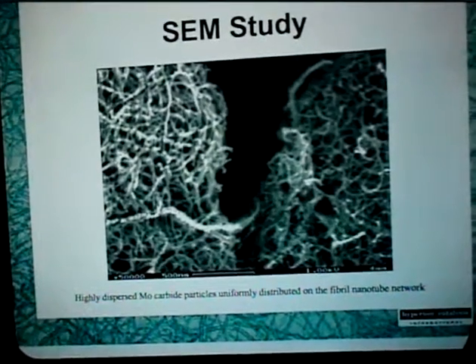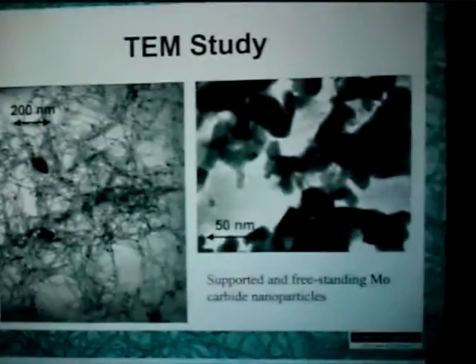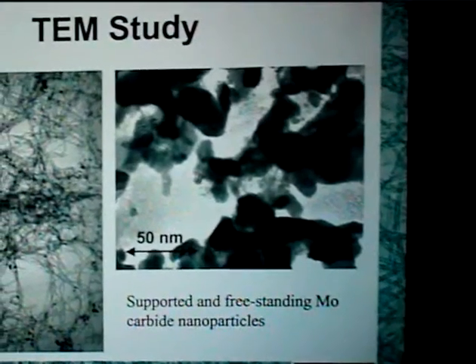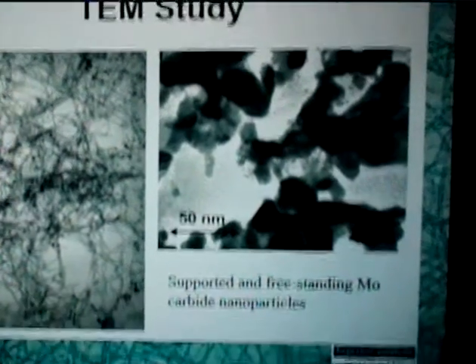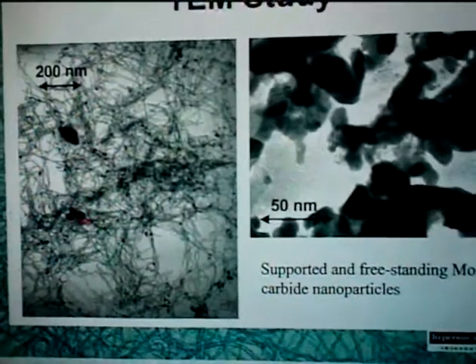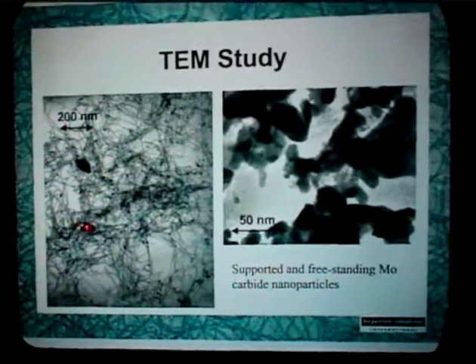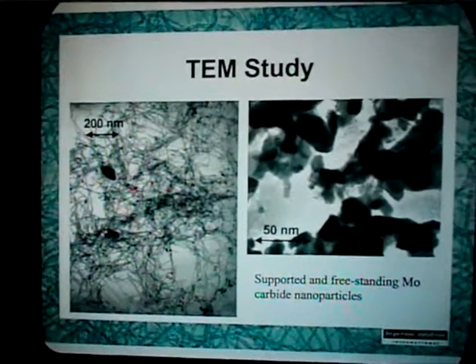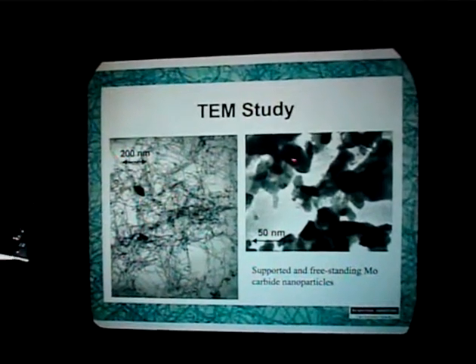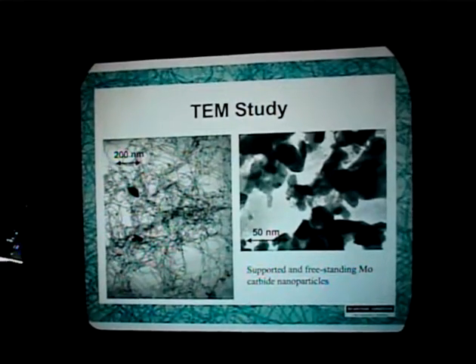So the important part is that we keep the structure of the fibril. And here is a much better picture, a TEM picture. Of course, those size of the particles depends on what is the loading that we have on the carbon. This is a low loading. Those are pretty large molybdenum carbide particles that are not representatives. You can see the small ones on the carbon. So this one has a small molybdenum to carbon ratio. So just I think it's 10% molybdenum per carbon. And we can see the free standing molybdenum carbide nanoparticles.